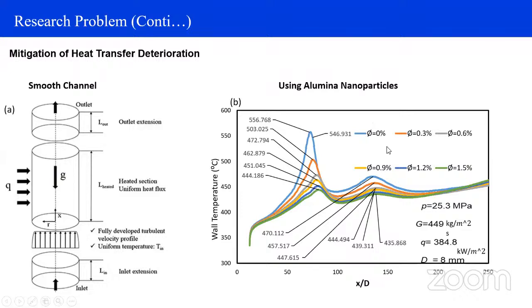If we see when there is no nanoparticle inside the base fluid, then the temperature is 556.768 at peak. And when we increase from 0% to 0.3% concentration of nanoparticles, then we see here the temperature is 503.025. It is clear from the figure that nanoparticles are helpful to reduce the deterioration of temperatures. Same like when we increase 0.3% to 0.6%, then the temperature is